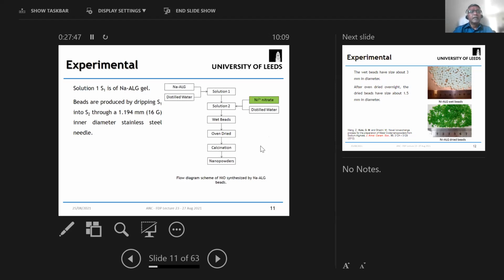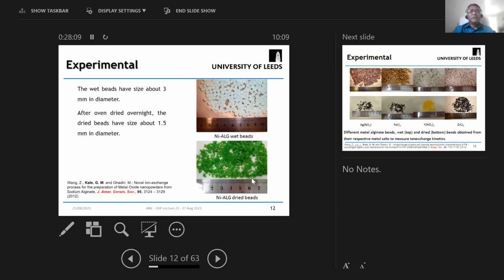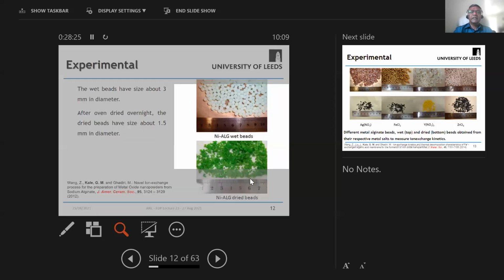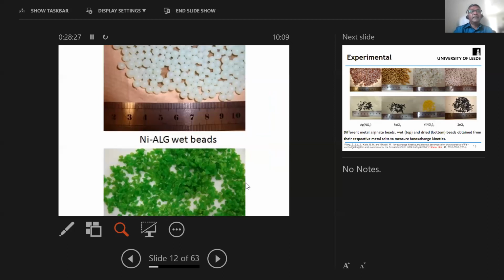We use typically a 16 gauge or 1.194 millimeter diameter syringe needle to squeeze out these wet beads. This particular slide shows you the beads that have been sieved containing nickel. So these are the ion exchange nickel beads, nickel alginate beads. And you can see that they are very, very spherical in shape. If I just enlarge this bit, they are very spherical in shape. These beads are produced from the runny gel by squeezing the beads out of the syringe.